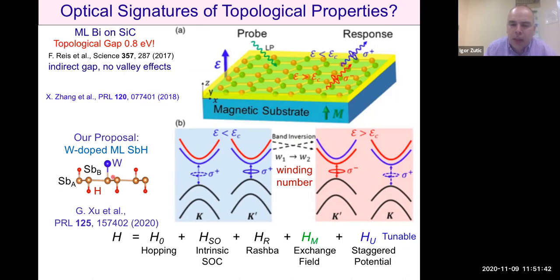So we hope that this will not just be a theoretical proposal, but that it would be experimentally implemented. However, it's still recent, so there is no, to the best of my knowledge, related measurement. What has been measured is that people, by looking at different structures, could suggest that they are consistent with the role of different winding numbers. So not on a single structure, not this tunability of band inversion, but let's say comparing bilayer and tri-layer graphene.